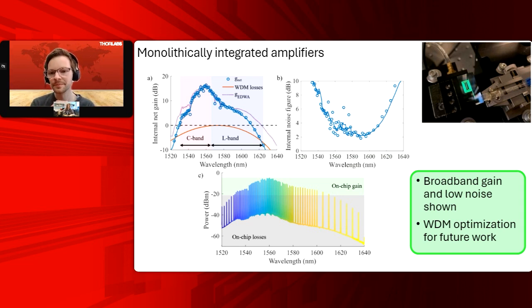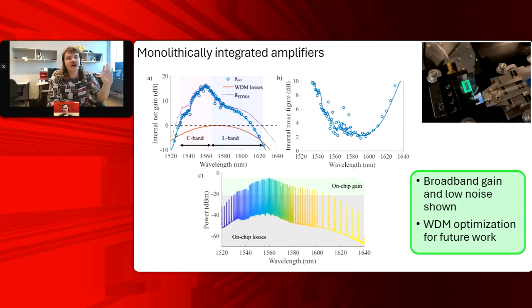It's a really good question, because at the beginning, I was showing amorphous, which was actually a lot of my past research on amorphous aluminum oxide. And now when we're talking about polycrystalline aluminum oxide, you want to start to imagine that the erbium has to sit in certain sites, right? And these certain sites are not crystalline, they're polycrystalline, because if you have crystalline aluminum oxide, the erbium is no longer ionized inside of it because of the symmetry. And for an ionized rare earth, you need non-centrosymmetric host materials.